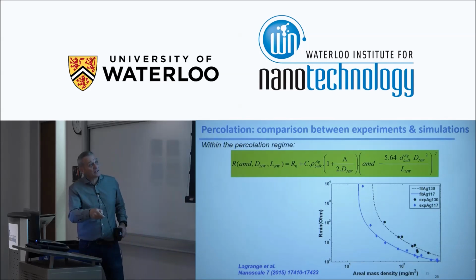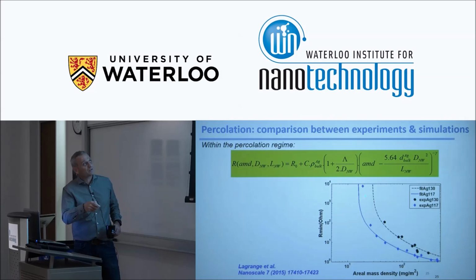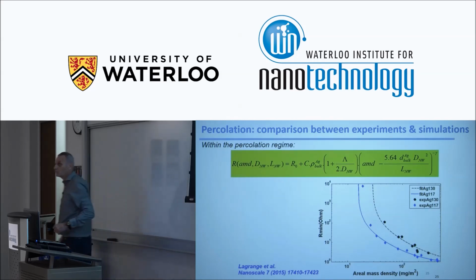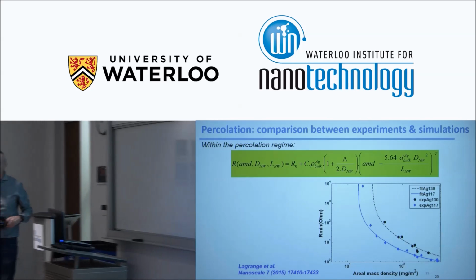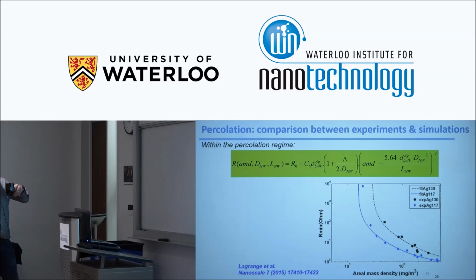And you can see that the fitting is pretty good, knowing that we have only one fitting parameter. And again, this is a very simple model. That's the simplest model we can imagine. So we are rather happy about that. And we can use this equation to have the minimum resistance, but as well, for sure, we can use another equation for measuring the optical transparency.